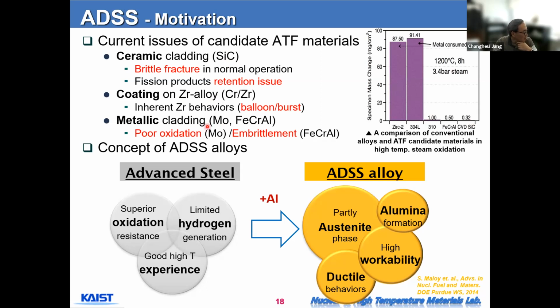And the metallic materials, molybdenum and the FeCrAl, are known to have poor oxidation resistance, and they have some embrittlement issues. So we tried to develop a better material to overcome those deficiencies. The idea was that because those materials are basically BCC materials, we add aluminum for high temperature oxidation resistance, and also maintain the duplex structure by increasing the amount of nickel. So we have a partially austenitic and partially ferritic structure, and alumina formation at high temperature, and we have better workability and ductile properties.